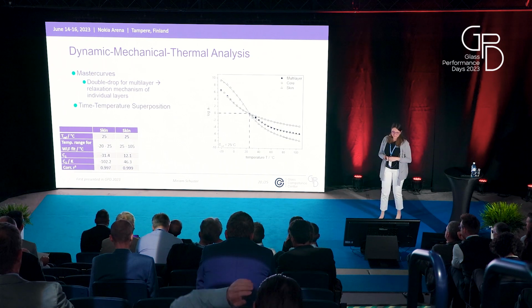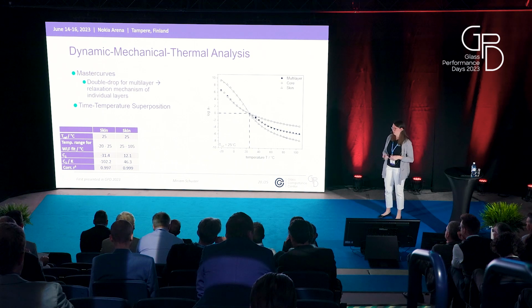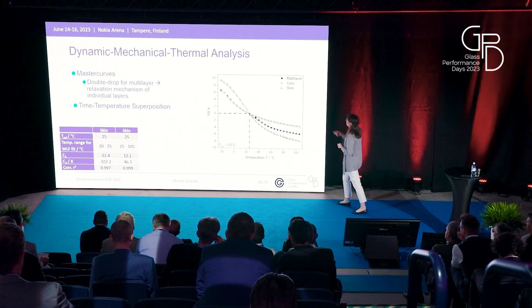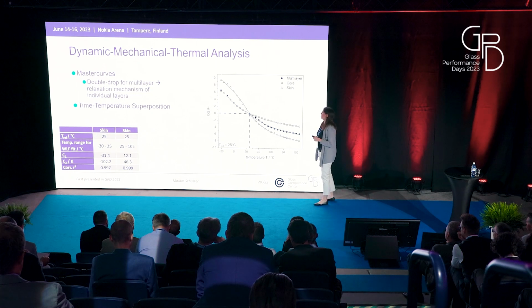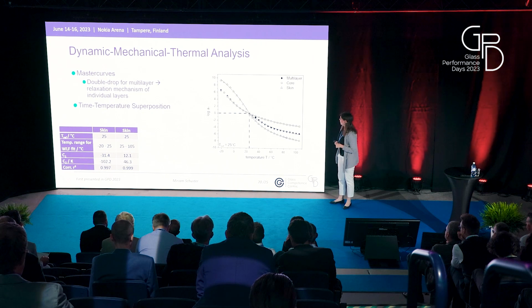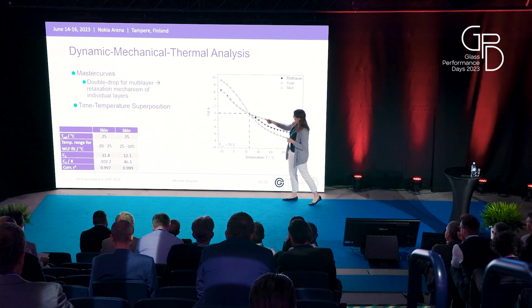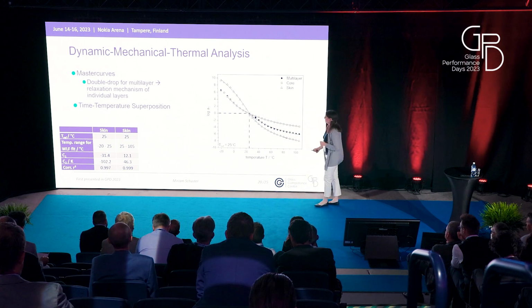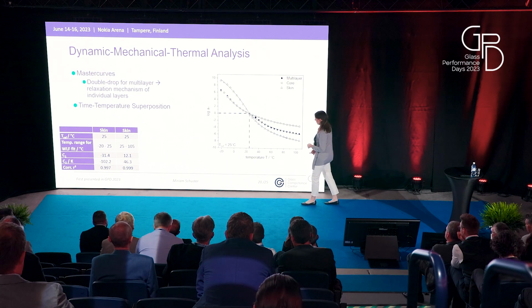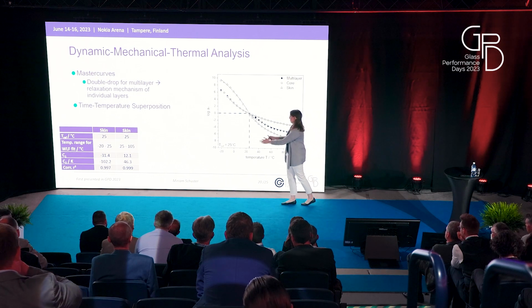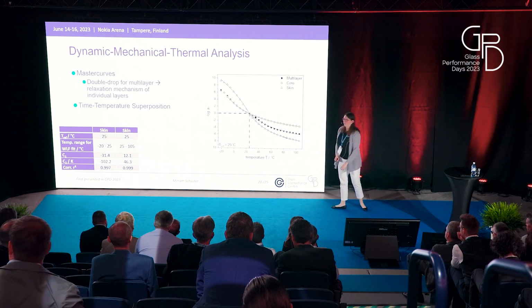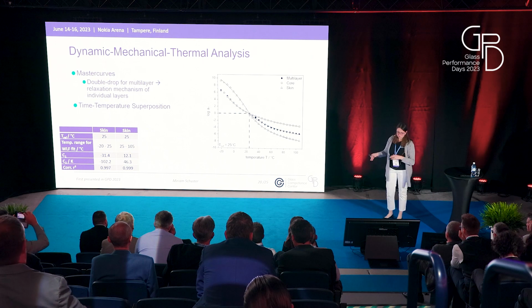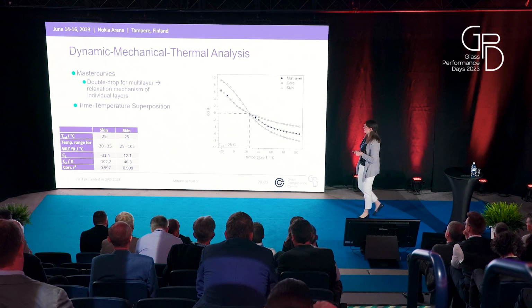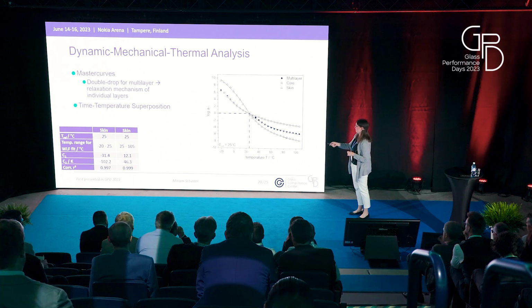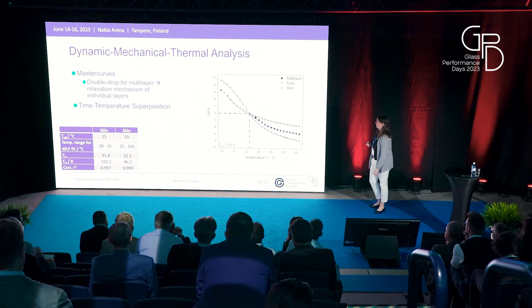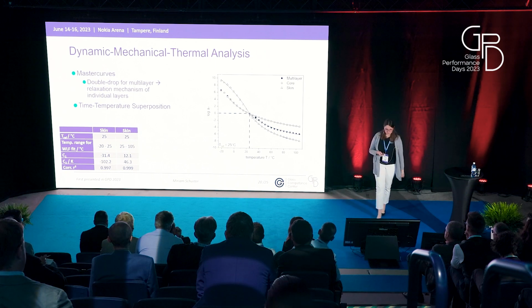Next, we had a look at the time-temperature superposition principle, or first at the shift factors, which are depicted here. The circles are for the multilayer, the square for the core, and the triangle for the skin. When looking at the triangles for the skin, we see that there's a change in curvature, and therefore we decided to look at two different temperature ranges, one above 25 degrees Celsius and one below 25 degrees Celsius, and then we fitted the WLF function to those two temperature ranges, and we also see that in the lower temperature area we have negative constants, while in the higher temperature area we have positive constants.